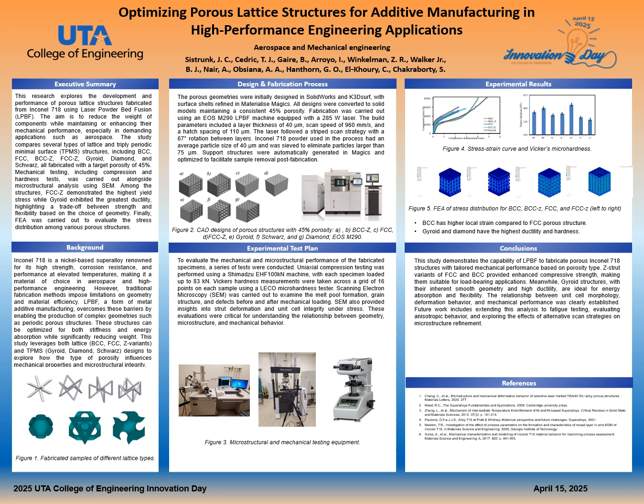After fabrication, the samples were tested mechanically and analyzed macroscopically. We conducted uniaxial compression tests using a Shimadzu testing machine and performed Vickers hardness measurements. Across 16-point grids, we also conducted scanning electron microscopy both before and after testing to observe microstructural features like melt pools, grain structures, and defects.